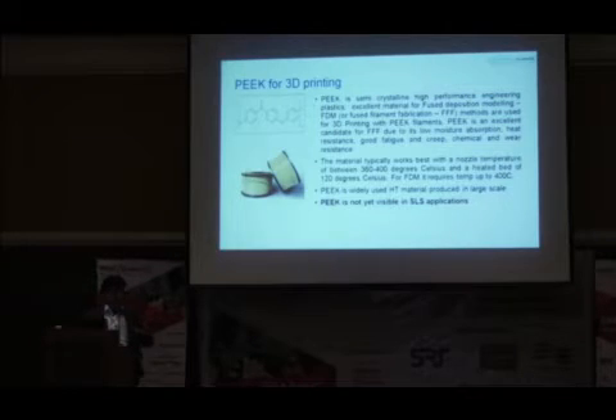This material is easy to process, so that's why these filaments are available in the market, and this material is quite widely visible in FDM filament type FFF technology. This material is very well visible, and we have experienced that since there are a lot of manufacturers available, but even though this material is not visible in laser sintering application, so we are wondering. So we assume there is a limitation with this material in laser sintering, probably the crystallization behavior of this material. So there you can go with other aryl ether ketone materials. So this material is available in filament, and it's not in laser sintering.